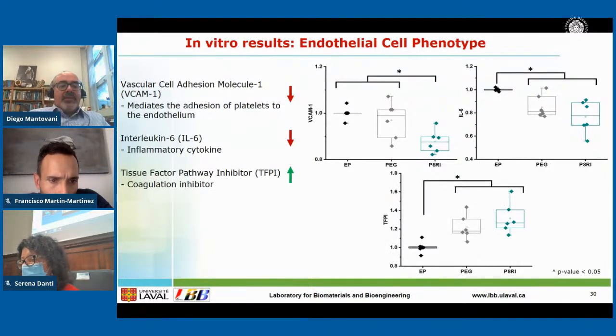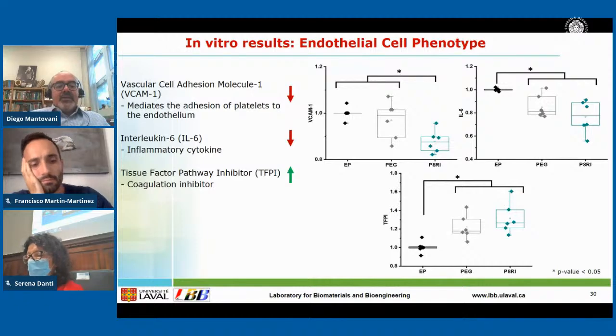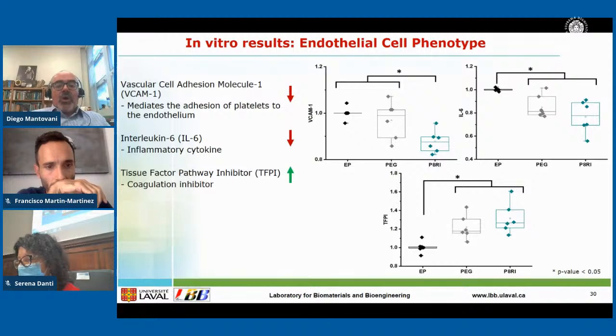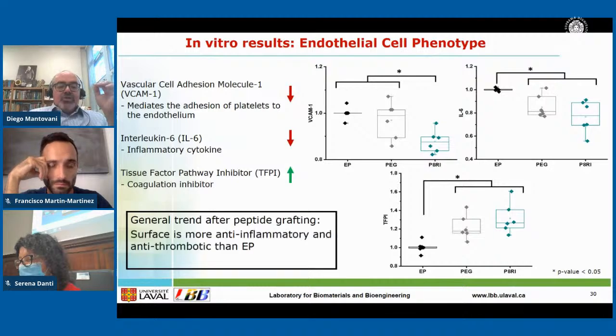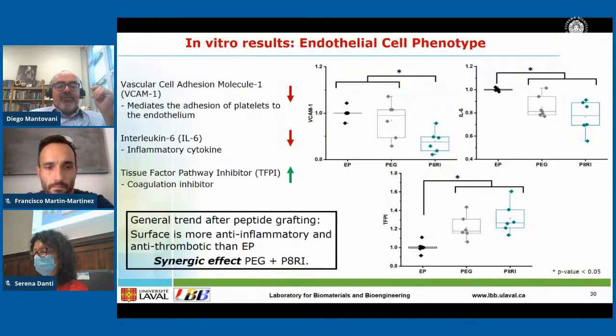phenotypes. So basically the vascular cell adhesion molecule VCAM1 decreased, and this means that the mediation of the adhesion of platelets to endothelium decreased, which is very positive for us. Interleukin 6 decreased. This means that the surface is less inflammatory, and the tissue factor pathway inhibitor TFPI increased. This is a coagulation inhibitor. These are three factors quite considered by cardiac surgeons. So in general, the surface after the grafting is more anti-inflammatory and anti-thrombotic than electropolished.